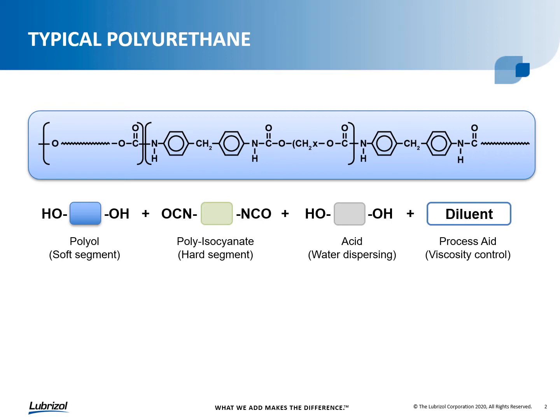So you need some type of a hydrophilic material, or in this case, acid, to help disperse that material into the water phase. And then the other common ingredient used in the manufacture of PUDs is a diluent or processing aid, because in making these prepolymers, they tend to be fairly viscous in nature, so you need something to help cut down the viscosity and make them easier to work with. NMP was very commonly used as a processing diluent, and it serves a dual purpose: it's both a great processing aid, very effective at reducing the viscosity of the prepolymers, and it also does a very good job at aiding in film formation when the coating is applied to the substrate.